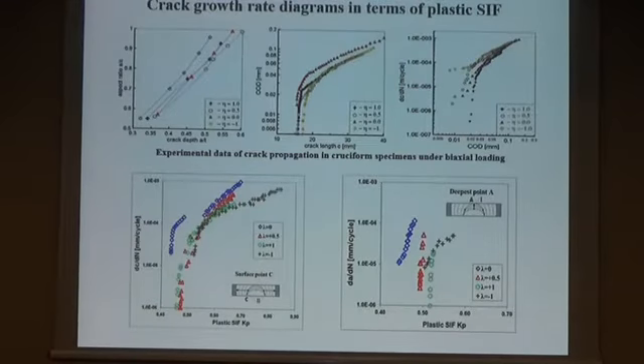So let's come back to our experimental data of crack propagation in cruciform specimens under biaxial loading. So you can see that there is a strong correlation between crack opening displacements and crack length. And these relationships between aspect ratio and crack depth as a function of crack opening displacement are very useful for automation of the experimental study of surface crack growth. And utilizing these relationships, we calculate the crack growth rate in the depth direction.